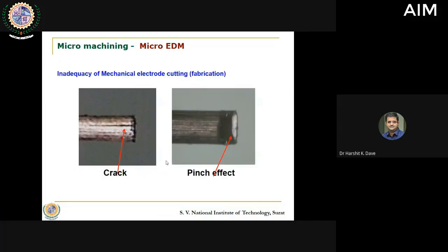Now when we tried to cut it with something like a mechanical scissor, crack initiated and propagated inside. This was fully cracked. And when we tried to cut it with a hacksaw blade with the minimum possible cutting condition, then also some pinch effect was visible at the end. So you can see over here it is not perfectly flat and perfect diameter with no discrepancy. So there is some pinch effect because of which eventually we could not get the proper shape of the end of this 0.3 mm diameter tungsten rod. Now if it is not perfectly cylindrical in shape, then there is no point in using it as an electrode. So this was a very big problem.